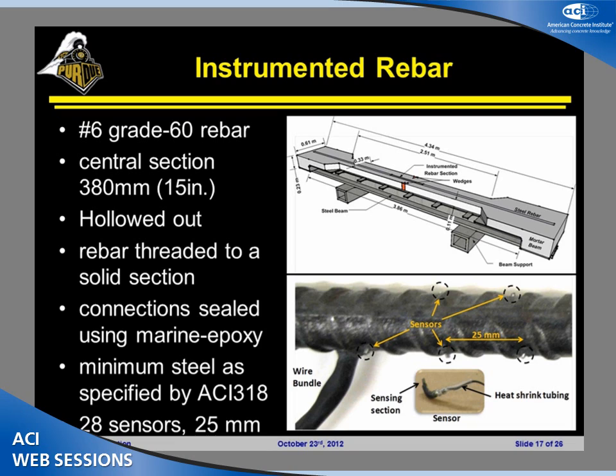The whole idea here is we hollowed this out and we tried to keep the minimum amount of steel that we would have, so that we've got about 28 sensors that are spaced about every inch apart as we work our way away from the surface of the crack.